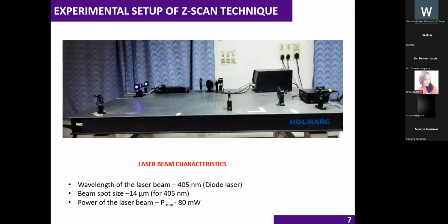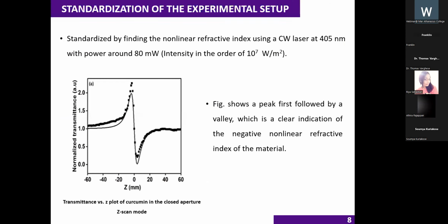The experimental setup that we have in our lab is shown here. The beam characteristics are: a 405 nanometer blue diode laser is used with a beam spot size of 14 micrometers, and the power of the beam used is 80 milliwatts. To standardize the setup, I took curcumin dye for this purpose. I mixed 1 mg curcumin powder in 5 ml water. Then the characterization is carried out using this diode laser, and I got a transmittance versus Z plot of the closed aperture Z-scan like this.